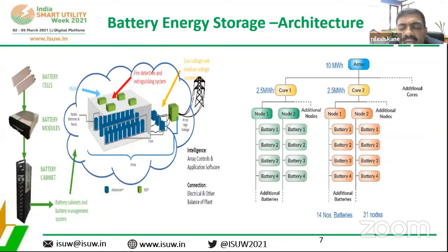So this is a simple architecture. It is a 10 megawatt hour system, and there are 4 cores of 2.5 megawatt hours each, because we have a typical topology of 66 by 11 kV grid on which we have 25 MVA transformers. So both the transformers are supported with 2 11 kV feeders interconnected with 2.5 megawatt hour cores. In every core, there are 2 nodes, and in every node, there are 14 batteries, and each battery has a capacity of 6.5 kilowatt hours. It is integrated with the smart inverters, and it is integrated appropriately through isolation transformers. Next slide.